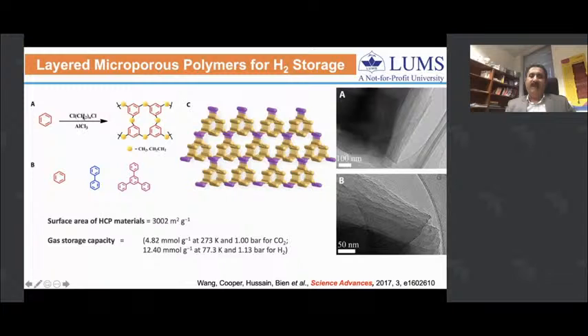And we, in fact, made use of that limitation to basically polymerize a variety of aromatic monomers into microporous polymers. These microporous polymers have huge surface area, even more than 3,000 meters square per gram, and they have the ability to store carbon dioxide and hydrogen, with decent storage capacity for both gases.